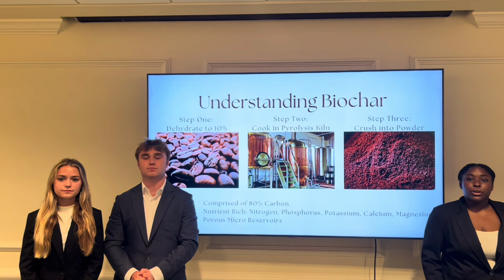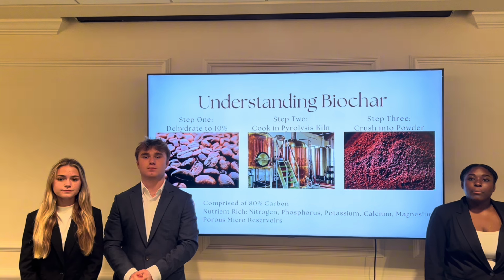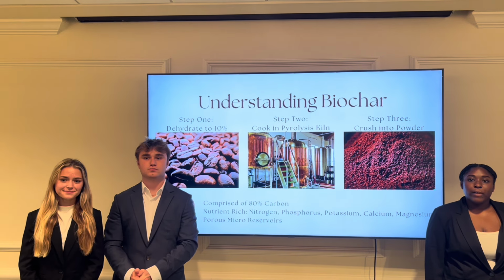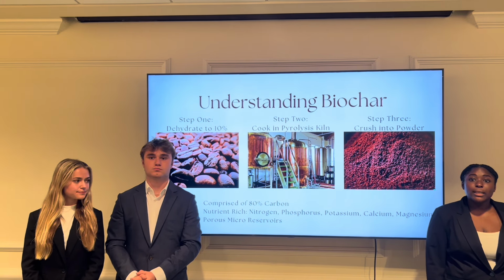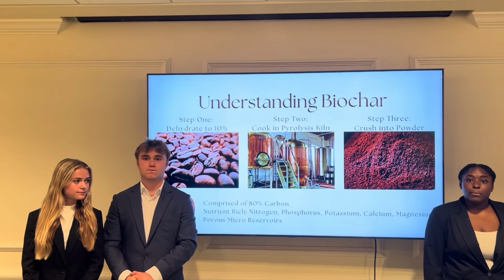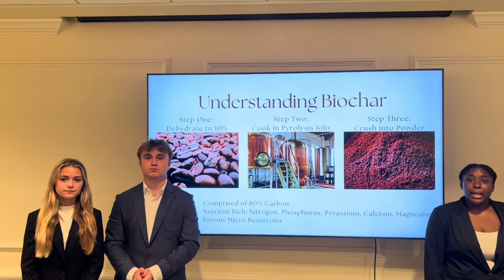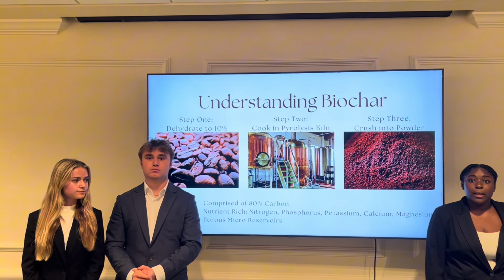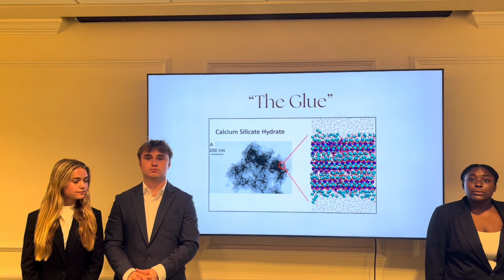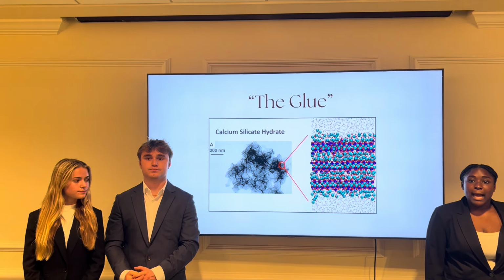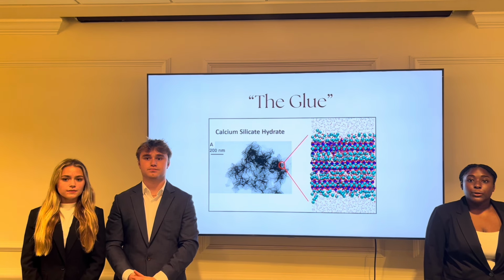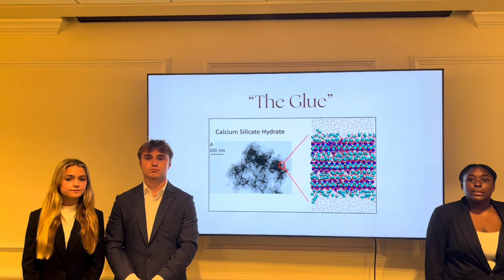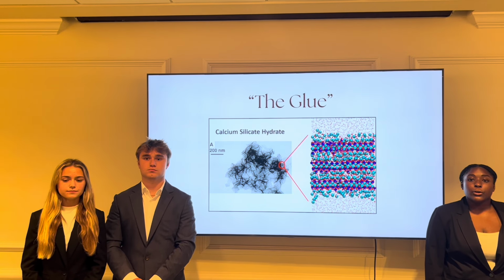But what is biochar? Biochar is created by carbonizing spent coffee grounds in a low oxygen environment, pyrolysis, producing a porous material that is over 80% carbon. This porous structure retains water and acts as microreservoirs within the concrete. During curing, it slowly releases water, strengthening calcium silicate hydrate gel formation, the glue that gives the concrete its strength, resulting in even more crack-resistant hardening.